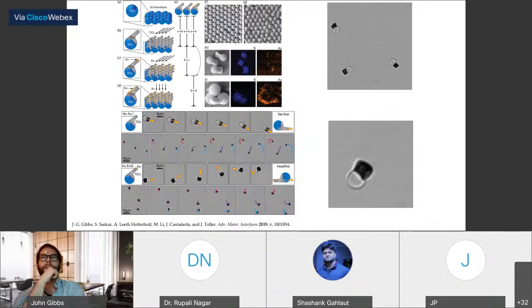So we did indeed find different types of behaviors. So really the primary one is that when we only have TiO2 alone, so we've already seen these structures in action here, you see that they start to move towards the tail of the structure. So it's moving towards the TiO2, which you can tell by looking at the structure itself, because you have the sphere and the TiO2 is the darker segment. So what we found out, though, is that if you put gold on the very end, it will actually switch the orientation of the motion. And so what you find in this other video here is that it actually switches directions. So just by adding that gold onto the end of the tail, it will change the behavior, right?